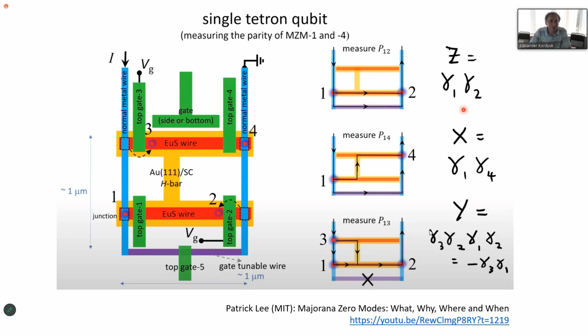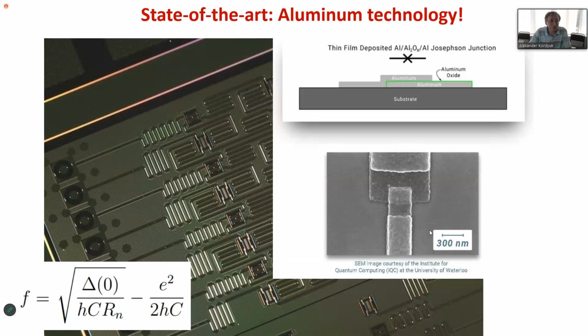They are much more stable than these states of qubits, superconducting qubits, which I described before. And now I switch to state-of-the-art technology, which is called aluminum technology. It is plain contacts. Aluminum is not the best material because Tc is very low, and it means the superconducting gap is very low, but it is very technological, and aluminum oxide is very reproducible, and therefore this is state-of-the-art technology now.